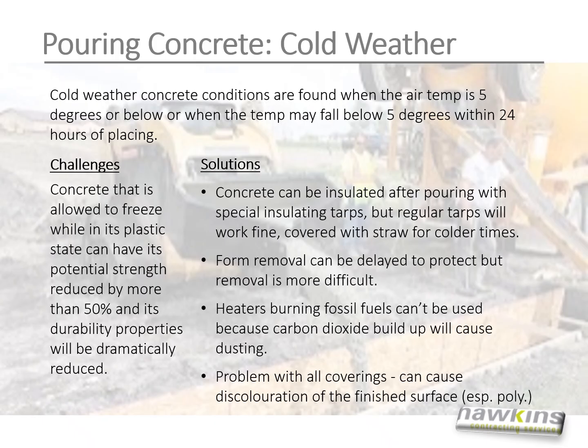Working with and pouring concrete in cold weather. Cold weather concrete conditions are found when the air temp is 5 degrees or below, or when the temp may fall below 5 degrees within 24 hours of placing. The challenges: concrete that is allowed to freeze while in its plastic state can have its potential strength reduced by more than 50%, and its durability properties will be dramatically reduced.